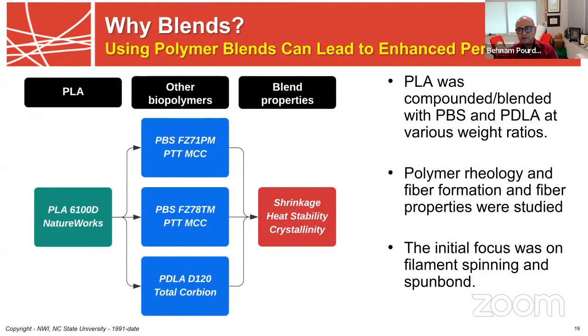Now, we use polymer blends, and I'm going to give you just a glimpse of what we have done in the work that Hamid carried on for about 4 years. We did not want to use plasticizers and other additives that could essentially render the biodegradability ineffective. So we're using other biopolymers. We're taking the classical 6100D, which is the crystalline version of the PLLA, and adding PBS, two different versions of PBS, and adding PDLA. And the reason we do that is that there is some literature that hinted at PBS and PDLA acting as nucleating agents for PLA.